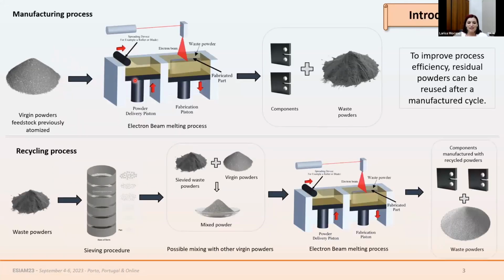So, as is known, the electron beam melting process starts with a metal powder as the material feedstock, which is previously atomized. If it's a virgin powder, then it's previously atomized according to one of the several existing methods. And then after the manufacturing process, we will obtain the desired components and a certain amount of waste powder. Also here, the waste powder is highlighted. And in order to keep low the production cost and to improve the process efficiency, it is possible to reuse this waste powder in the next manufacturing cycle.